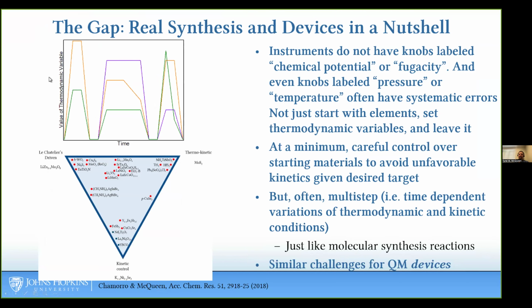Or said another way, the reality is that real syntheses for most real materials today are not setting the thermodynamic parameters at some value and leaving it, and they're not just continuously changing them all uniformly. It's much more complicated. It changes three different thermodynamic constraints, maybe: composition, temperature, pressure are the obvious ones, but there are many others as well. Electrochemical potential, for example. And you control those as a function of time in a very controlled way to make things, right? And this, combined with the fact that there are often systematic errors and gradients and all these kinds of things, makes this very, very hard to treat using current methods.